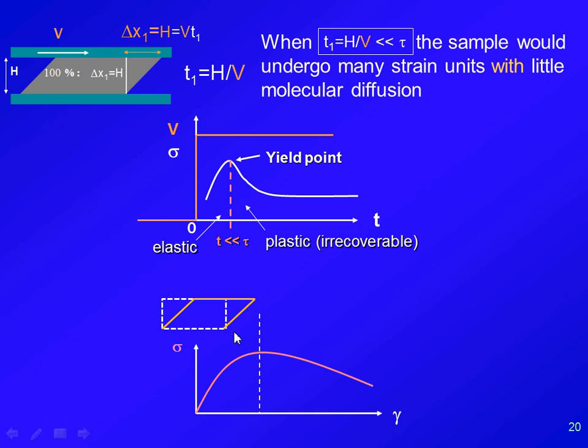Because you can shear your sample anywhere before this maximum. And then there are instruments that can let go, in the sense you let the stress go free. That's called let go. Let it so-called undergo elastic recovery. In other words, this is elastic deformation, as I explained. So they actually really go back. But if you shear beyond the maximum and then let stress go free, in other words, turn off the stress, your sample does not recover to its original position. So clearly, there is elastic dominant deformation on the left, and irreversible deformation to the right of the maximum.